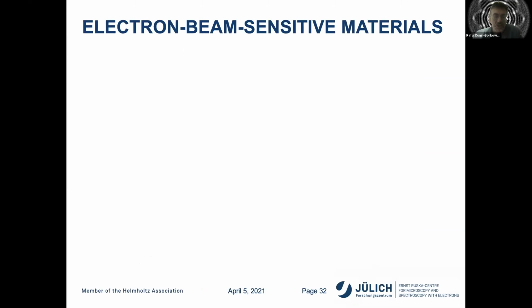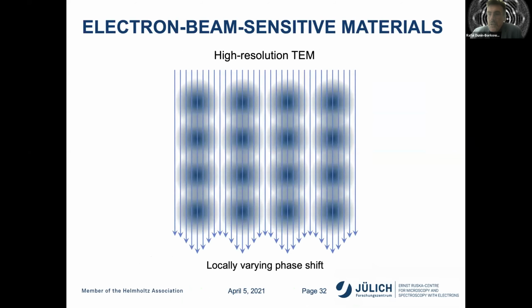And the final topic I wanted to touch on is electron beam sensitive materials. And here, I wanted to come back to a point which may not have been apparent from the beginning, which is that in phase contrast techniques applied at atomic spatial resolution, whether it's in high resolution TEM or whether it's in structural biology, we ideally want to image the phase of the electron wave, the phase shift, rather than changes in amplitude contrast. And a technique which allows us to record the phase directly is what we would ideally like to use, rather than, for example, defocusing and then inferring the phase shift indirectly. And I mentioned at the beginning that there are a number of different phase contrast techniques that we can use.